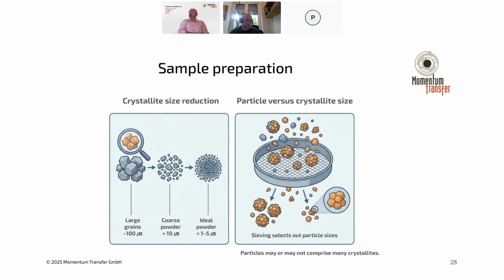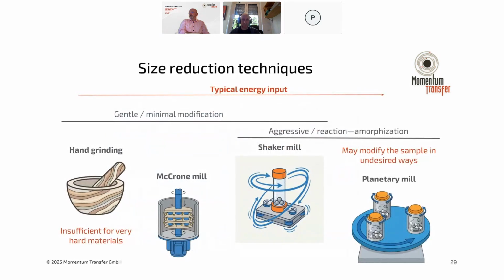So you can sieve these particles out, grind them out selectively and add them back in as an example. And there are different ways to do size reduction, from hand grinding to the standard method, which is McCrone milling, which is essentially roller mills that are low energy, up to more aggressive shaker and planetary mills. And these really depend on the type of material that you're working with.